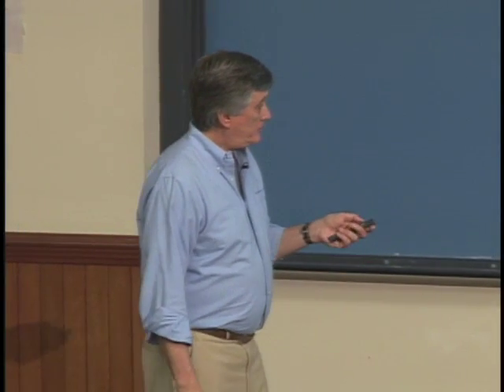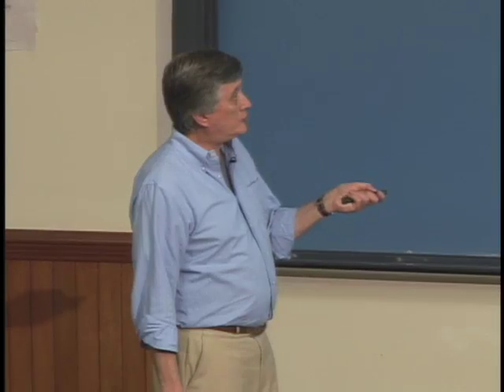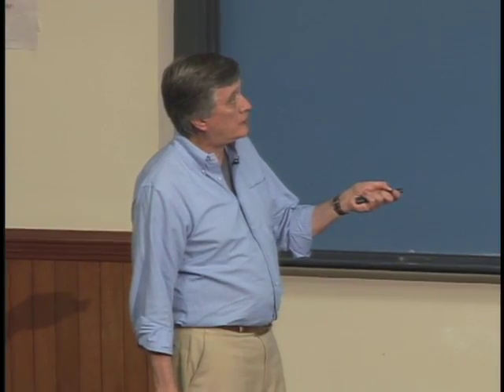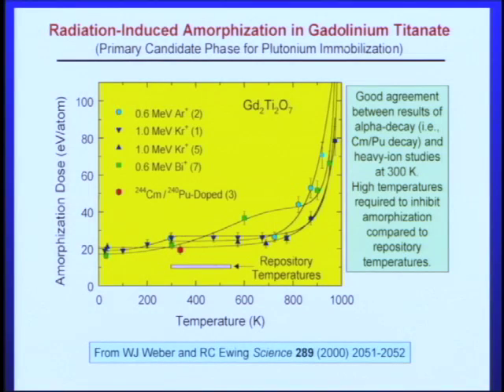From the ion beam experiments, we get the dose as a function of temperature, where this dose is the dose for amorphization, and you can see the curves are flat for a while and then they bend upwards at higher temperatures, and that's just where the annealing dominates. At high temperatures, the damage anneals quickly. Everyone on the dance floor is so agitated they find their partner and you get back to where you wanted to start. Sorry for hammering on this analogy, or metaphor, but I enjoy it.